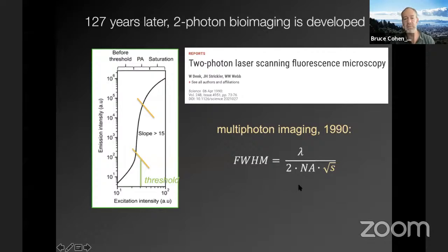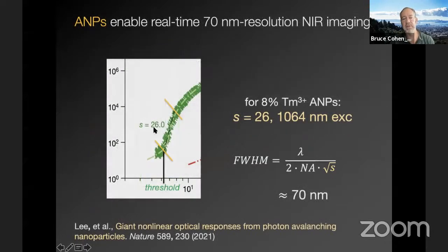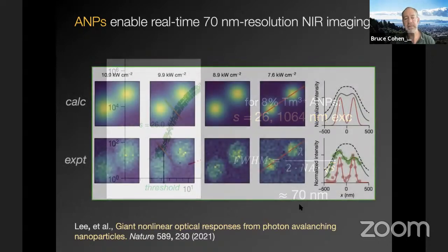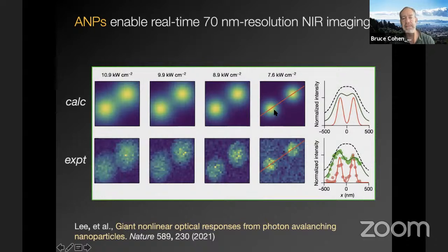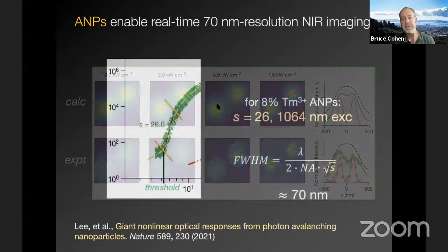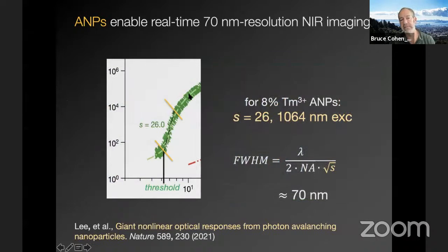But you see, what I'm getting at is now with our resolution, if you have a slope of 26, theoretically, for 1064 excitation, we should be getting a resolution, so not super resolution, of 70 nanometers. And in fact, that's what happens. So the top is calculations showing what this would look like if you have two of these nanoparticles 300 nanometers apart and you're changing the excitation wavelength, and that's actually the experiment that we have. If you notice here, the slope goes down.